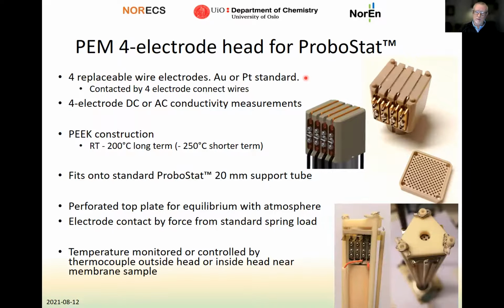The standard supplied by us is gold or platinum. And these are then contacted by 4 electrode connect wires here on the sides, on this side and the other side of the head. It has a PEEK construction, which means that the materials here can tolerate 200 degrees long term, or up to 250 degrees on a shorter term, which is higher than most commercial test systems otherwise.